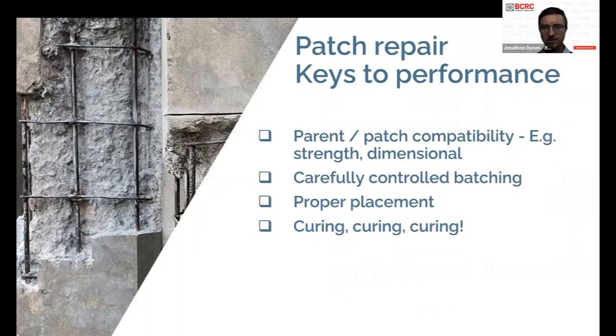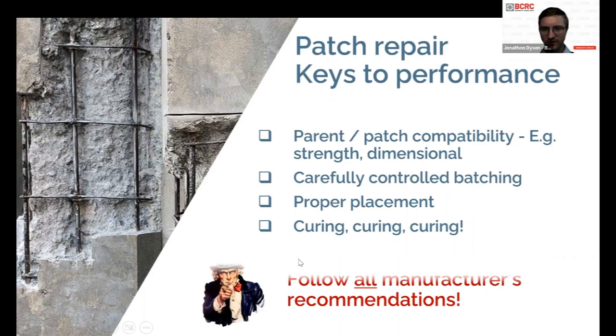Proper placement obviously is important, and then curing. Once you've placed your patch repair material, curing is just so important in terms of achieving the performance characteristics that are needed, that are specified for that patch repair material. And oftentimes curing is the last thing, and it's forgotten or not paid enough attention to. And you won't achieve the specification, and the design of the repair is done assuming a certain level of performance is going to be achieved from the patch repair product. When I say performance, I mean things like strength. I mean things like bond between the patch material and the substrate, all these sorts of things. So it's important to follow the specification, but it's also important to follow all the manufacturer's recommendations of any product that you're using.